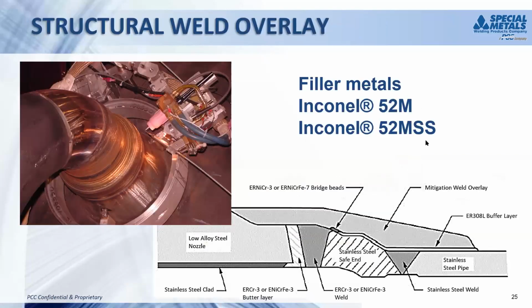So as you can see here, this is a structural weld overlay, which was done not so much for corrosion on the outside, but as you can see, these safe ends were a pretty elaborate amount of different alloys and different welds. You can see on the bottom, there's a low alloy steel that had a stainless layer of weld metal, then a nickel alloy, then you had a stainless steel safe end, and some other components. With all that dissimilar welding going on, there was a very high probability or problem for stress corrosion cracking.